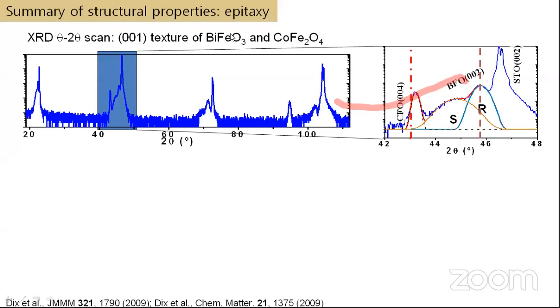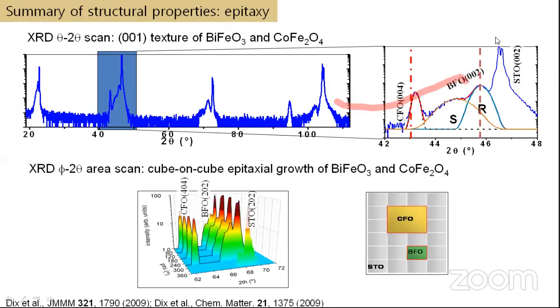So on a strontium titanate substrate, this is the X-ray plot between 20 and 100 degrees. These are the highest peaks, the substrate peaks. If you enlarge this region, it looks like this. You have a substrate peak, you have your cobalt ferrite peak, you have your bismuth ferrite peak.